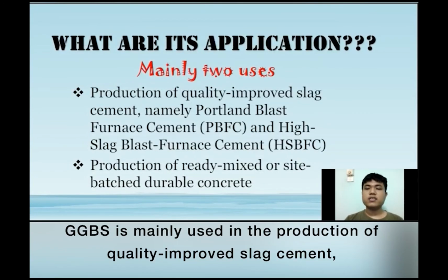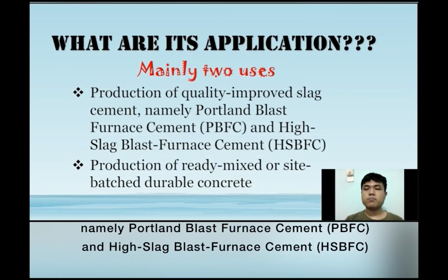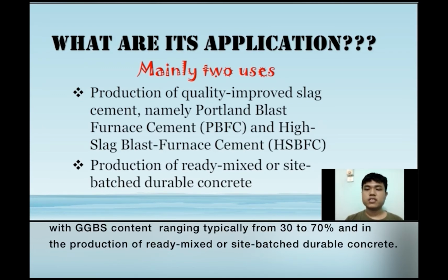GGBS is mainly used in the production of quality improved slag cement, namely Portland blast furnace cement (PBFC) and high slag blast furnace cement (HSBFC), with GGBS content ranging typically from 30 to 70%, and in the production of ready-mix or site batch durable concrete.